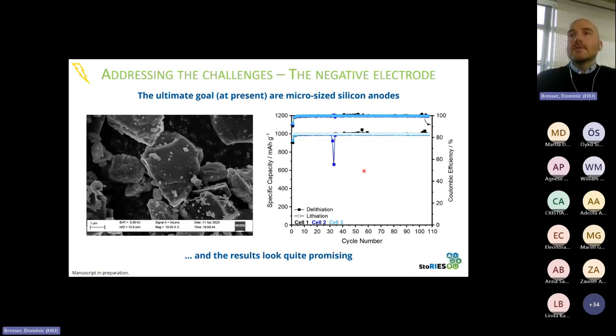And this is just a lab example apparently, in so-called half cells, with the lithium metal counter electrode. But you can see that the lithiation and delithiation process, especially if limited somehow, is very reversible. So even for these micro-sized particles, there is, I would say, a reasonable hope that we can have the transition from graphite to such silicon particles also in industrial cells eventually. So still at the beginning, but a pretty promising pathway.